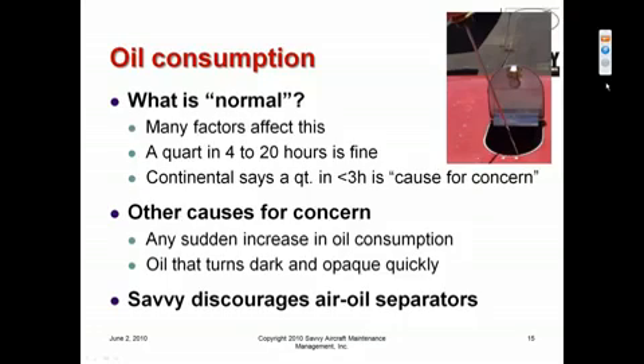There are certain engines that have small air oil separators that were installed by the factory, and with those we don't have much choice because they're required for airworthiness. But we strongly discourage adding aftermarket air oil separators, particularly the big effective ones like the Airwolf, for example, because they do a very good job of minimizing apparent oil consumption or loss of oil, I guess you'd say, but at significant expense, and we just don't think it's a very good idea.